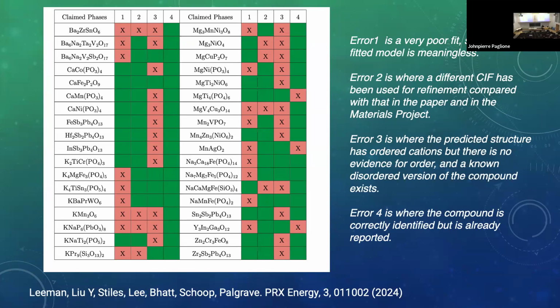Error 3 is the predicted structure has ordered cations, but there's no evidence for that order, and a disordered version of the structure exists. This might be a little bit complicated, and this is the most common error. About 2/3 of these materials have this, so I'm going to walk you through this. And then error 4 is that they did actually correctly identify the material, but it was already reported. So they must have missed this in the literature.